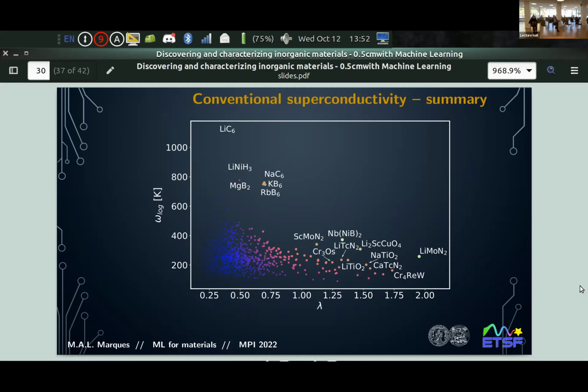There are some false positives here, actually, that came out that have instabilities, so that were not caught in the first round of calculations. That's the case of this compound here. It was a very big disappointment because it's actually a cuprate, and having a cuprate with 40 Kelvin normal superconductivity would be quite interesting, but it's an instability. So this is also an instability. But we have here a funny one: lithium molybdenum nitride. And we have other ones.